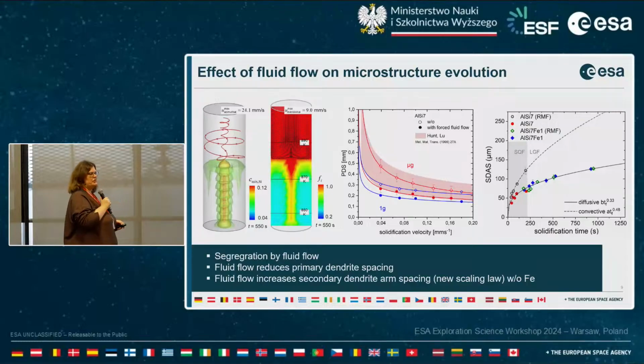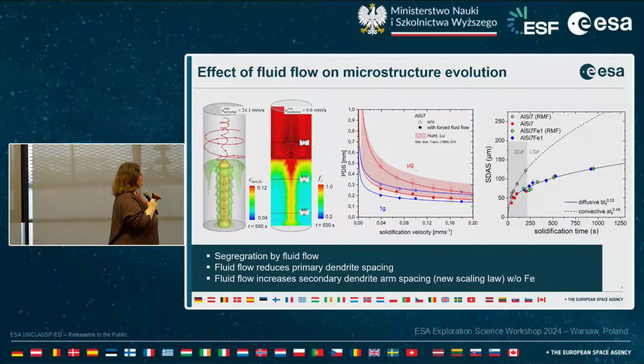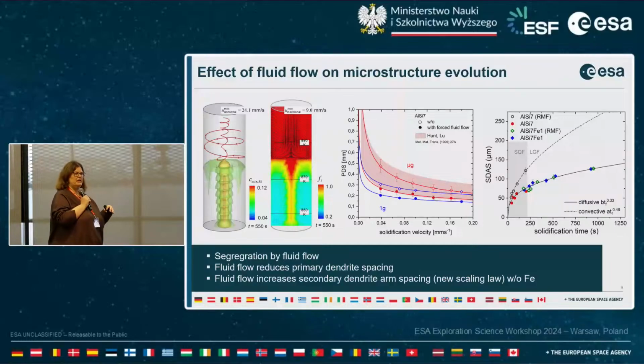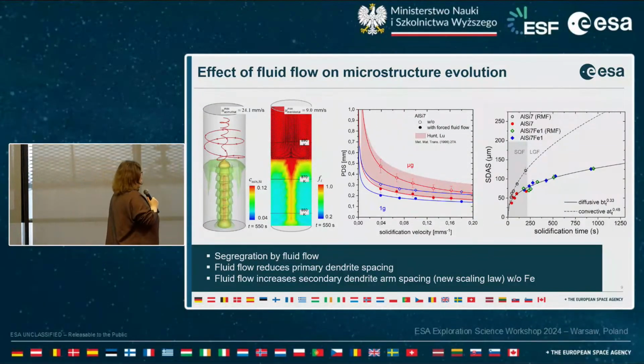This was somehow astonishing because we will see, as before, a change of the fluid flow, a change of the primary spacing for such types of alloys. The dendrites interact with the fluid flow, but deeper into the mush, the secondary dendrite arm spacings were not changed. This was somehow astonishing for us. We say, okay, at the top we see something, but going down deeper into the network, we see no effect. So what was the reason for this?